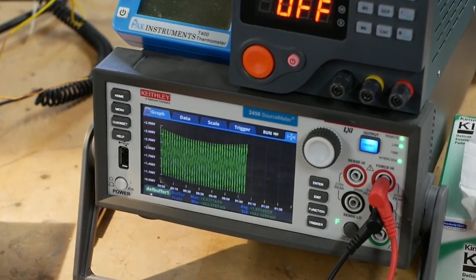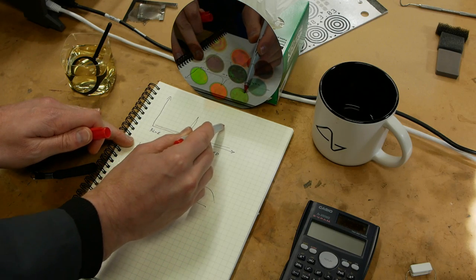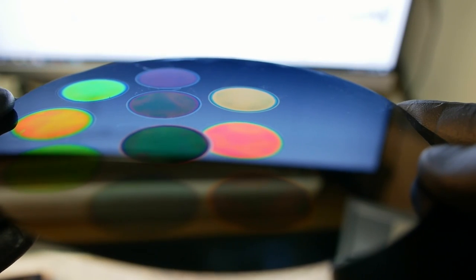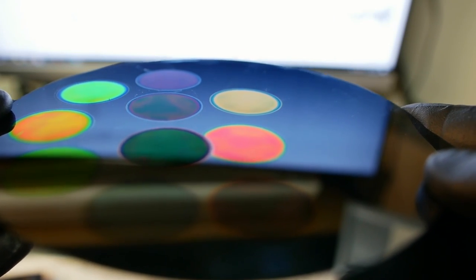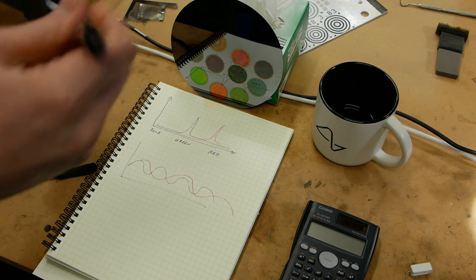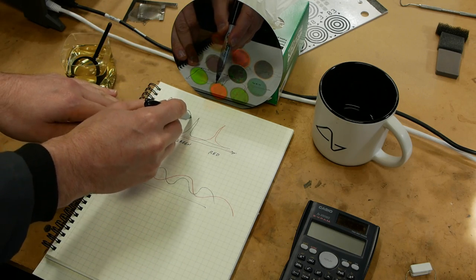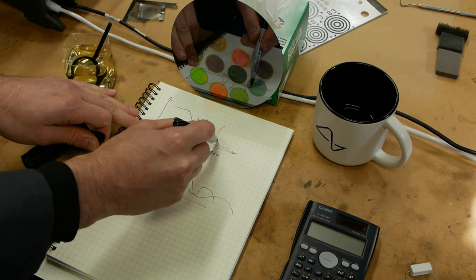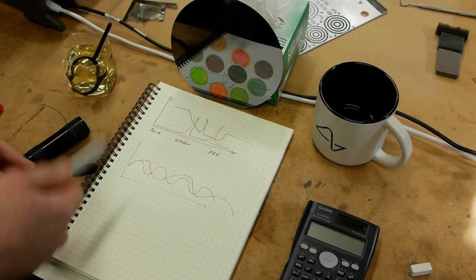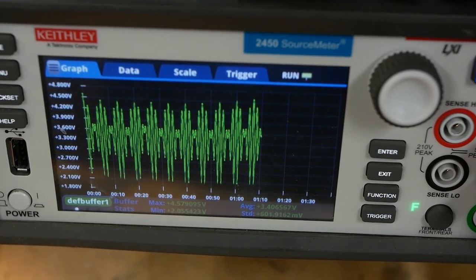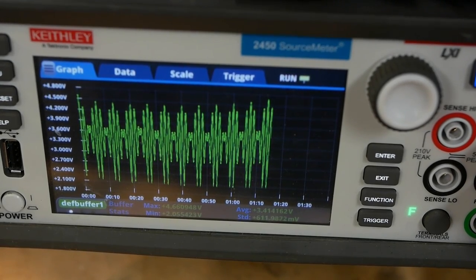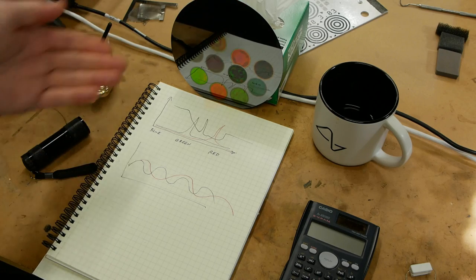And if we wanted a red one, it would be almost the same thing, spike it red, and then we would end up with a longer wavelength for red. And that's exactly what I did to do this. And what's cool is that this actually works for any spectral response you want. You could draw something completely arbitrary, a lot of blue, and then it's down, and then there's a spike, and then it's back up again. Anything you can draw, take the Fourier transform, and then that waveform becomes what we use to create the filter. So this is a really cool technique that gives you a tremendous amount of power over what you want to create spectrally.